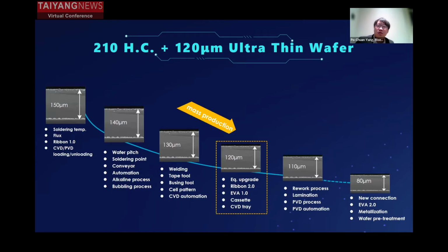So here I would like to talk about thin wafer production status. Actually, we started from 150 micrometer wafer. After that, we decreased 10 micrometer, and it takes several weeks to solve the issue during production, not only cell, but also module production. Then decreasing to 130, it takes roughly longer, and then 120 takes half a year. So right now we have a clear path to 80 micrometer wafer thickness, and we are confident we can do mass production in the near future.